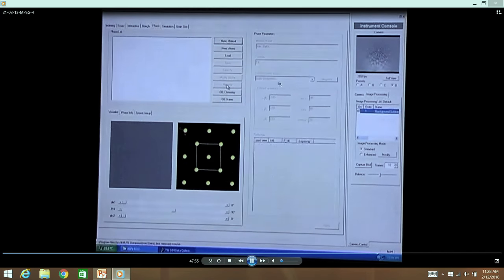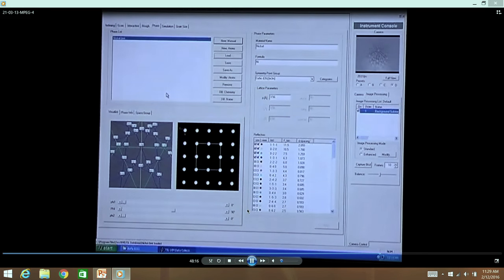when you talk about representation of the bulk texture or bulk orientation and so on. And normally what happens is, I will just briefly tell you how the analysis is done by this software. The electron beam goes, you click the mouse and it produces the Kikuchi line. If you know the crystal system of the specimen, in this case it is nickel, a database belonging to nickel is selected, and then the software will generate an orientation